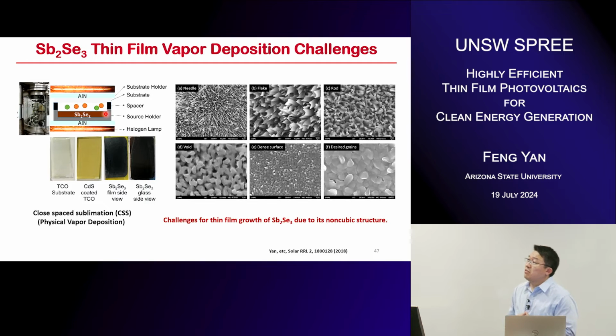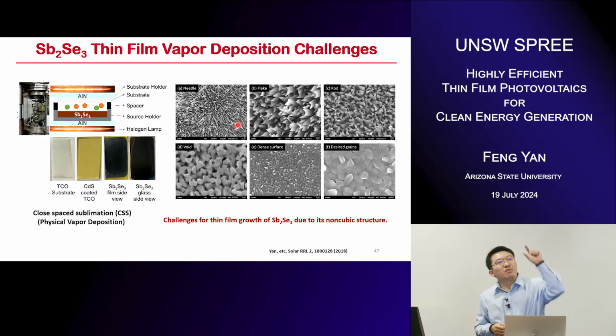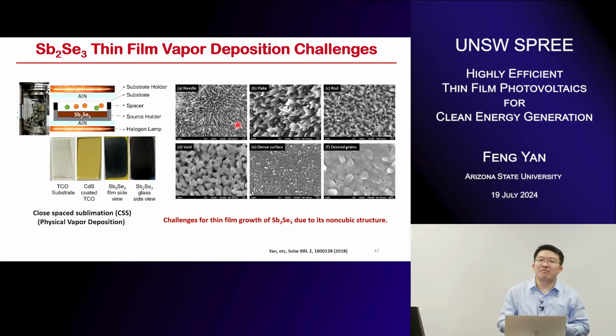Initially, we grew this film. The first graduate student in my group was almost crying when they saw this film, right? There was no way to make a good device. The efficiency was 0, right? So it's pretty challenging. You can see that the film looks like needles. Maybe it looks like some flakes. It's also like some rods. And if you hold the film up to the light, it has a lot of pinholes.